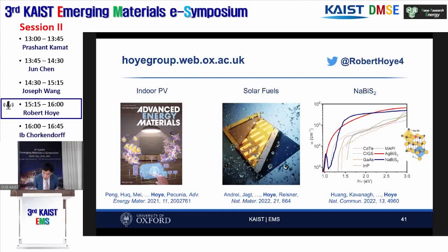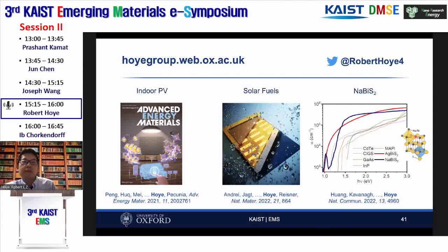Absolutely. With the lead halide perovskites, one of the strengths is that you can finely tune the properties over a wide range through the composition, and you can do exactly the same with bismuth-based compounds. So, for example, with bismuth oxyiodide, you can tune the band gap by changing the halide from iodine to bromine to chlorine. And similarly, for surface defects, you can passivate those using very similar passivating agents to what has been developed with the lead halide perovskites, because the electronic and chemical environments are very similar between these bismuth and lead-based compounds.